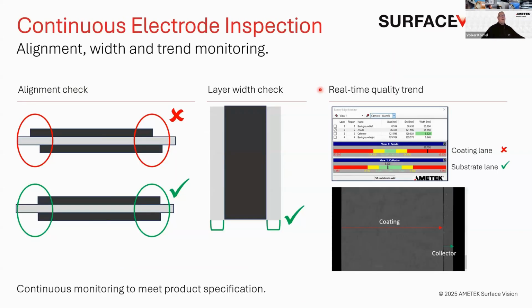But beside the detection, the customer also wants to have a kind of width monitoring. So you have now an image of the surface. So in this case, it's a coated area, and then you have the substrate on the right side. And the customer was interested in the coating lane width and the substrate lane width. And since we have a continuous inspection, this is a relevant factor, which we can also show to the customer. What is not part of this presentation is the calibration part. Also, you have to have good tools and techniques and calibration rulers so that the measurements for the width take into account that the number fulfills the specification of your needs.